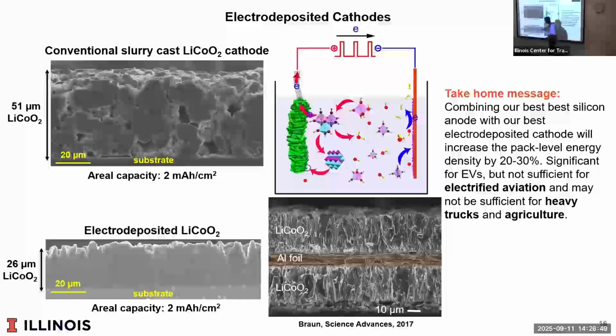Here's what we do. We electroplate it. Instead of making it from a slurry, we grow it just like you would electroplate a metal, from the bottom up. When we electroplate it, we get a sort of single crystal, a solid material. Because we grow it from the bottom up, we can grow the crystal so it's oriented this way, and these are the fast directions for the lithium and the electron. So now instead of random particles, we have highly oriented pathways, and material can go up and down. This is just a picture on aluminum foil, and here it is on the two sides of the aluminum. If you get this, you get another 20 or 30% increase at the pack.